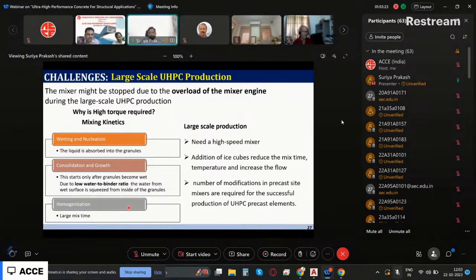So if you're using regular mixers, then the mixing time will increase like anything because we are using a low water-to-binder ratio. First, everything has to be wetted and nucleation has to be done. Then consolidation and growth should happen. Then the homogenization takes place over a very long mixing time. So for large-scale production, we need a high-speed mixer, and the addition of ice cubes reduces the mixing time and temperature, and increases the flow. A number of modifications in the precast site mixes are required before we can successfully produce UHPC precast elements.